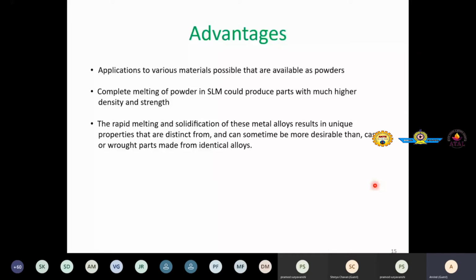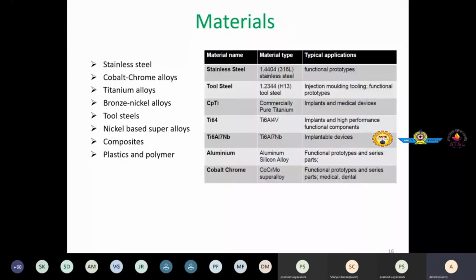We'll see that rapid melting and solidification in such a small melt pool leads to very fine microstructure, and fine microstructure leads to very good strength. At present, different materials are being used in the SLM process, starting from stainless steel, which is used for functional prototypes, tool steel, used for injection molding and functional prototypes, commercially pure titanium, for implants and medical devices, Ti64 alloy, again for implants and high performance functional components, then titanium niobium alloy, for implantable devices, then aluminum alloy, for functional prototypes, series parts and automotive applications. Cobalt chrome alloy is for functional prototypes and medical and dental applications.